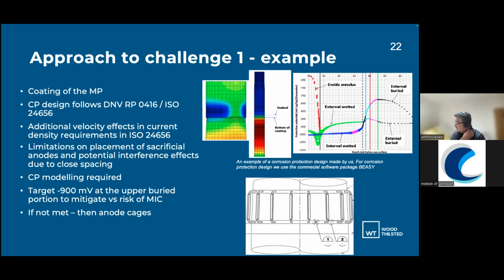But what we see is that because of the clustering of the anodes in one elevation, we do need CP modeling. Here is just an example of what we did on one of our projects, whereby we clumped the anodes right at the top there, whereby this is this blue here. The section that's in green is actually where the boat landing was. There is no anode around there. And we see how that attenuates all the way down to the bottom. And what we see is that at this water depth, which is around 30 meters, we do still see protection potential of around minus 900 millivolts, which is good for mitigating against MIC as well, especially in the upper buried zone.